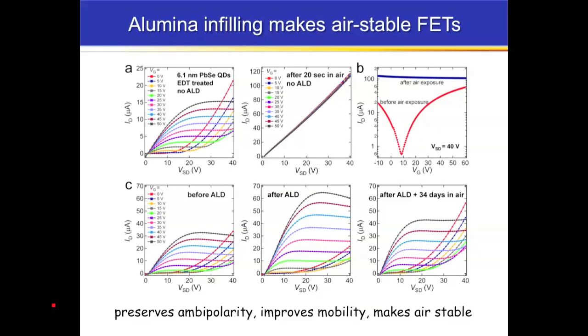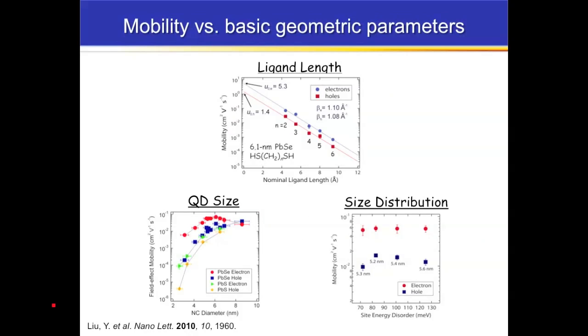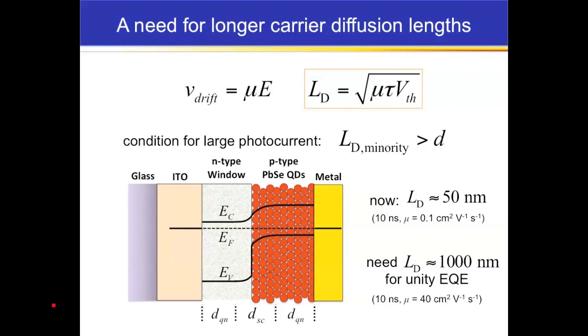What I should have pointed out back here is that these mobility values that we're able to reach, the highest mobilities that we see, are on the order of 0.1 centimeters squared per volt second. And that is not super high. Okay, so amorphous silicon can reach about 1 or 2 centimeters squared per volt second. And there's a big effort in the field right now to improve carrier diffusion lengths.